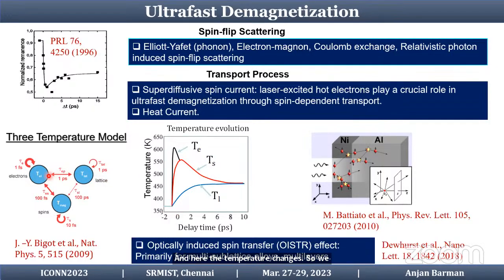So we already told you that the three different baths have different temperatures. So you can see the electron temperature, spin temperature, and lattice temperature, and how they evolve in time, the lattice temperature being the slowest one, and it catches up after some time. So actually the physical heating of the system occurs on a picosecond time scale, whereas the non-thermal processes like electron and spin occur on a much faster time scale.